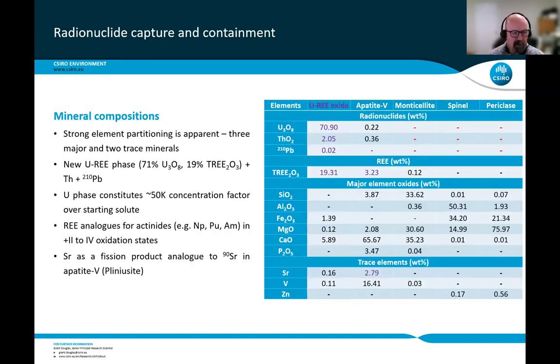So now if we look at the compositions, and I won't labour this too much, it's really just looking at the first column there, the uranium rare earth oxide. That contains around 71% U3O8. It contains pretty much all of the thorium, all of the lead-210, so it's got all of the radionuclides pretty much associated with it. It's got all of the rare earths, the total rare earth oxides there of 19.3%, and it's got a few other minor major and trace elements associated with it.